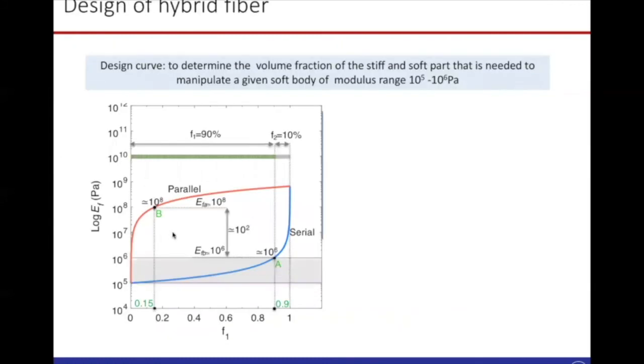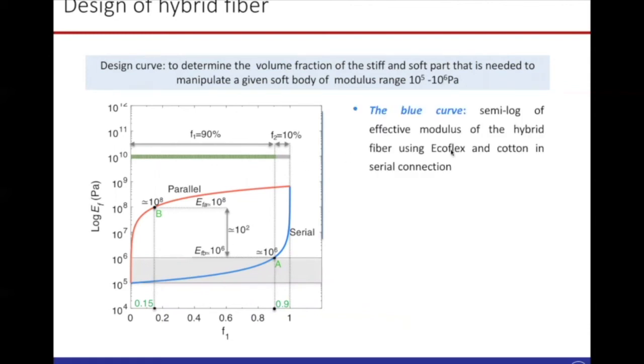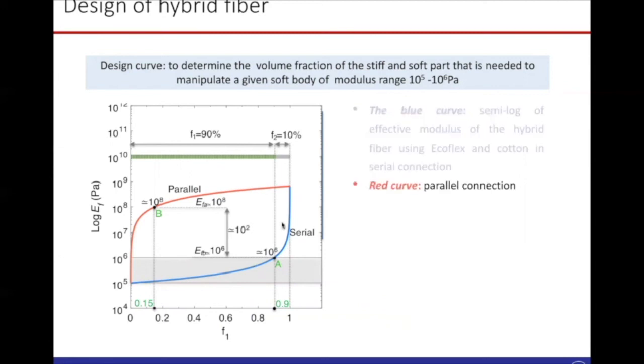Before that, we need to design this hybrid fiber, for which we use this graph. Designing means you need to determine the volume fraction of the stiff and soft part. So here the blue curve indicates the semi-log plot of the effective stiffness of the hybrid fiber using Ecoflex and cotton in serial connection. And the red curve indicates that in parallel connection. And the gray area here indicates the modulus of your soft body that you want to manipulate.